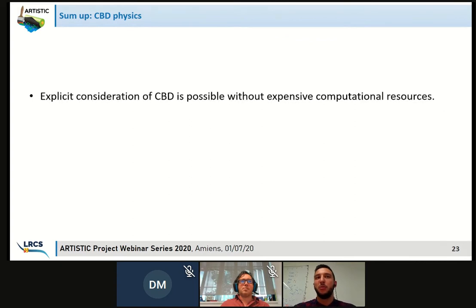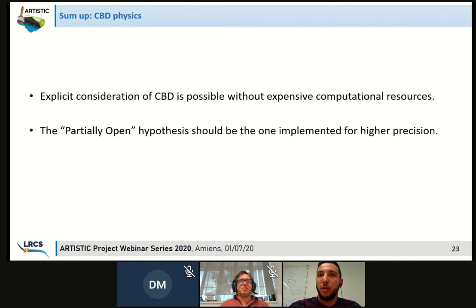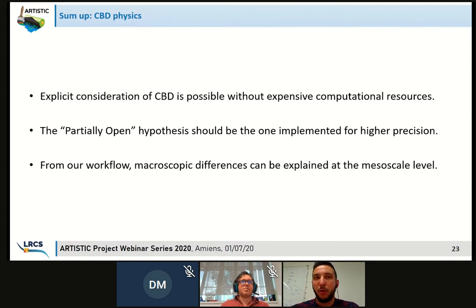So a quick sum up about this CBD physics. We show that this explicit consideration of CBD is possible without having like a supercomputer or even a server, because all the simulations were performed on my computer, so 32 gigabyte computer. Then we believe that the partially open hypothesis is the one that will be implemented for higher precision. We shouldn't consider the CBD to be blocking for the electrolyte. And then from our workflow, we were able to show that we can explain, for instance, how the difference in capacities because of the mesoscopic effect of CBD on the active material particles.